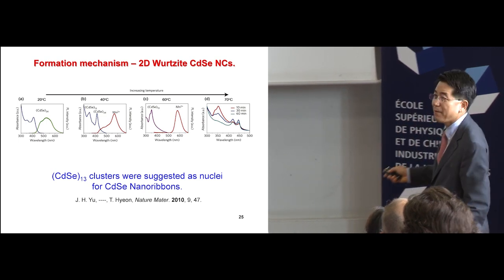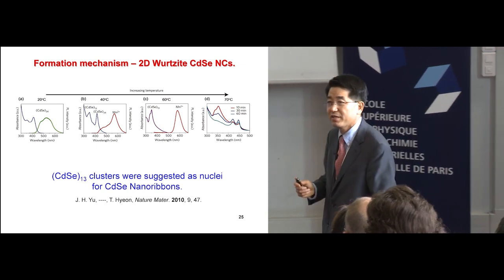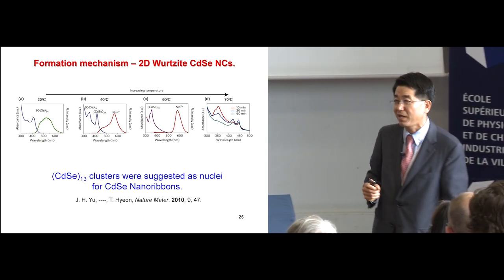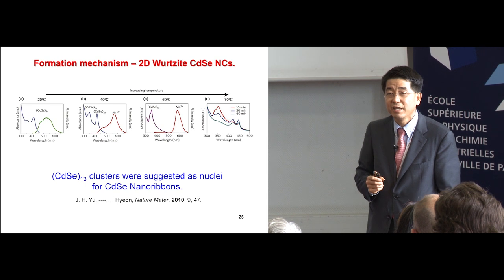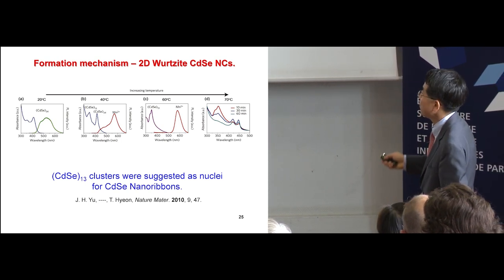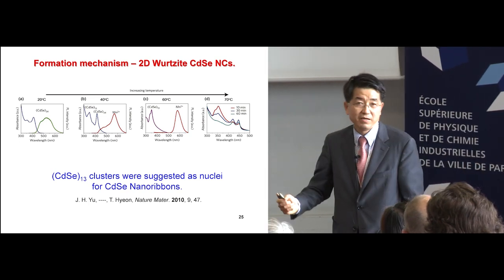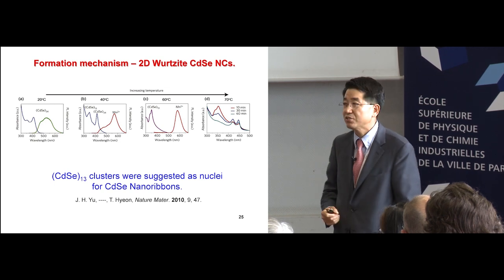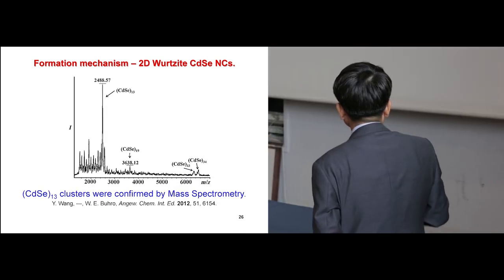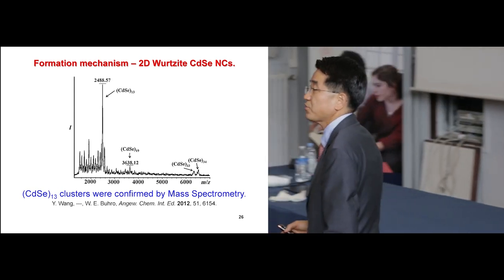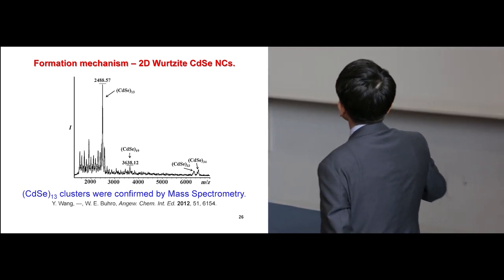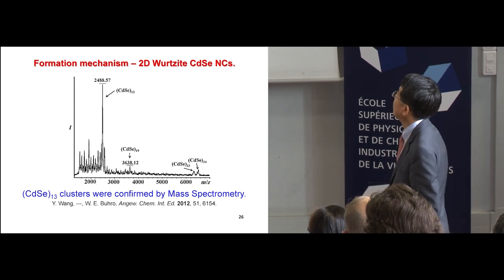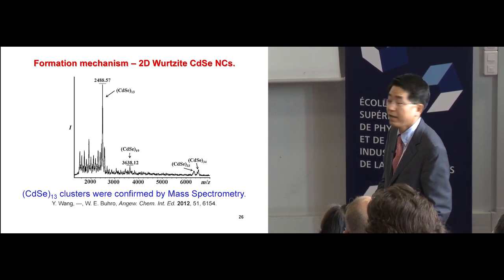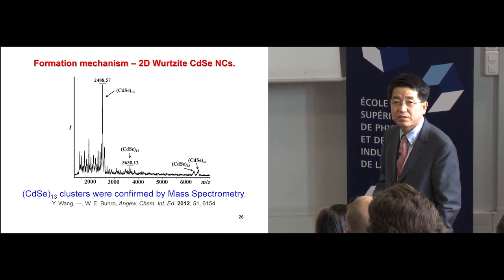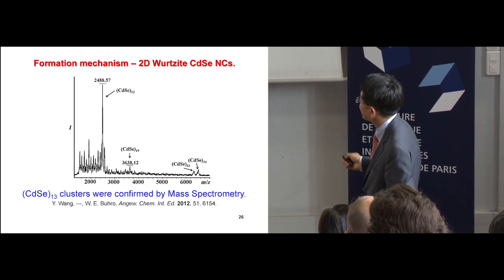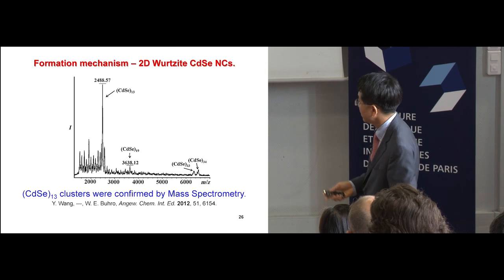So we think what happened is, what's the starting point, okay? Yesterday, Jonathan Owen gave an interesting talk about the nucleation and growth process. That's quite interesting. So this is what you think: the starting point is CdSe13. This is what you think is the monomer, the seed for crystallization to make a nanoplatelet structure. I'm going to get back to this later on. Very recently, a couple of years ago, Bill Buhro could see these CdSe13 clusters during the wurtzite structure formation, all right? And then he could see the larger clusters, the 33 and 34 clusters, and he claimed that this is transformed to this, that's what he said.